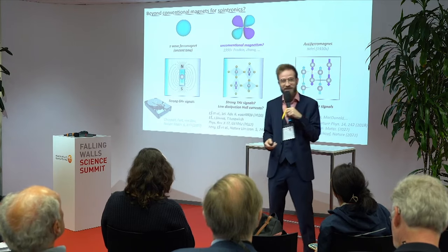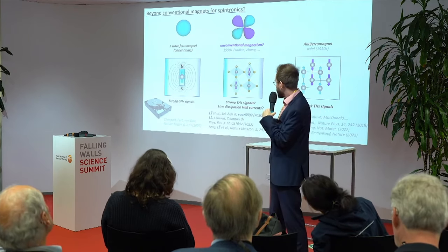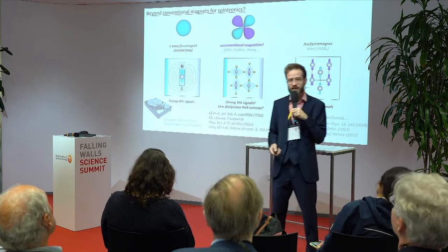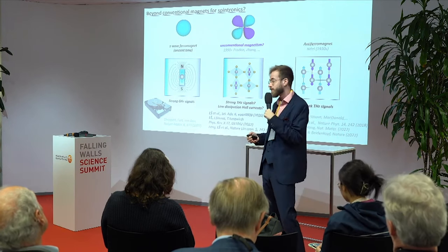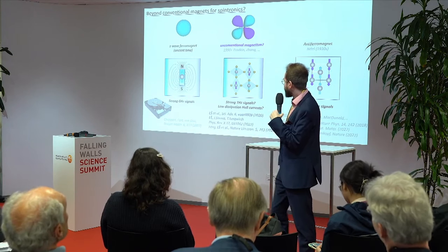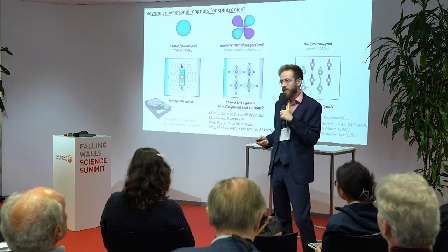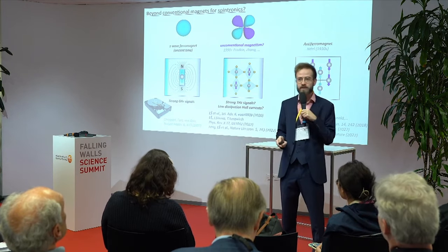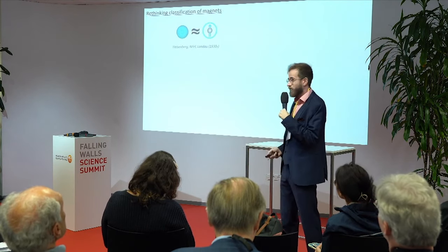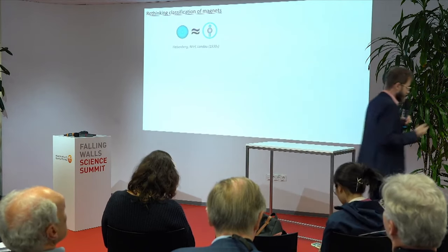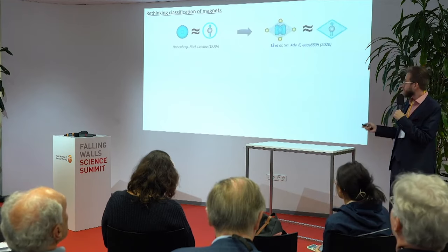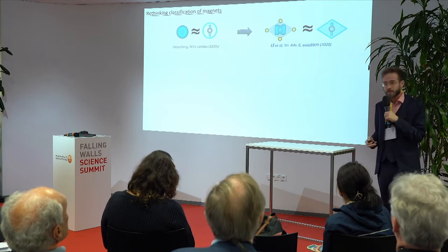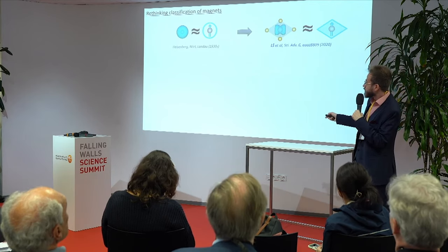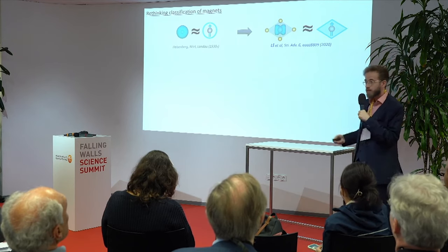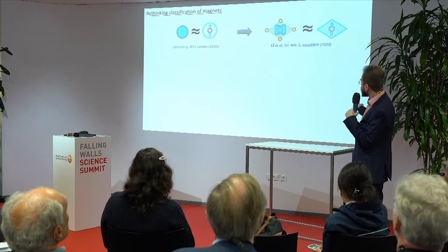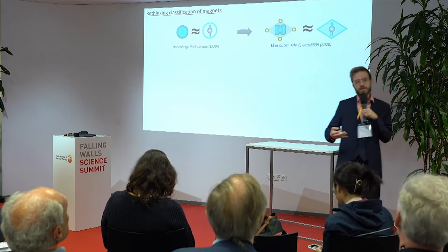And the unexpected direction came from spintronics, where we found out that when we decorate this antiparallel, antiferromagnetic-like ordering with additional extra non-magnetic atoms, we end up with something that actually behaves exactly like this. And I will try to explain now why it is so interesting and why such a type of magnetic matter is different from the two conventional ones. So, for understanding that, we need to revisit the way we think about magnets in two basic ways. The first is that it's important to consider also the spatial anisotropy of the magnetization density. While in many magnets the spin density is isotropic, in these more unconventional magnets it's strongly anisotropic, and that means that on top of the local magnetization vector, you need to consider the anisotropy,